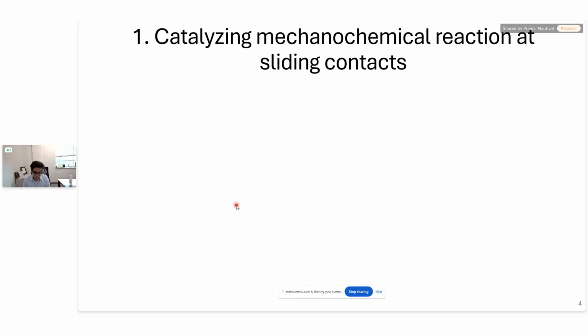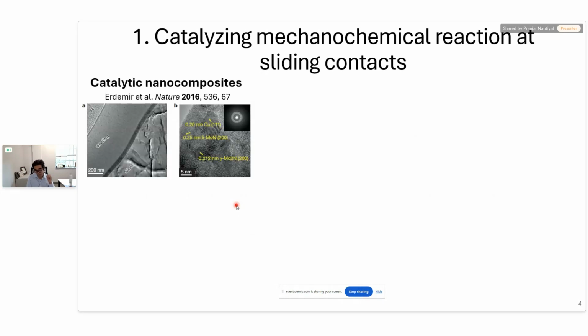So catalysts are widely used in thermochemistry because they can assist chemical reactions and accelerate the formation of products. They do that by reducing the effective energy barrier for chemical reactions and providing surface sites for the reactants to attach and react. The concept of catalysis was extended to design lubricated systems or tribological systems by Professor Ali Erdemir and co-workers in 2016, where they designed catalytic nanocomposites that consist of transition metal nanocrystals like copper and transition metal nitrides like molybdenum nitride in this case.